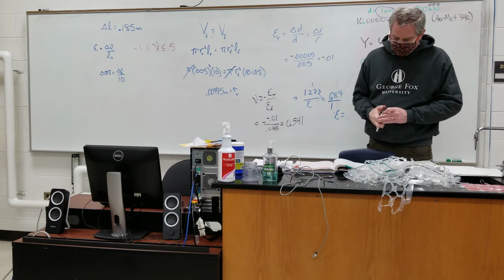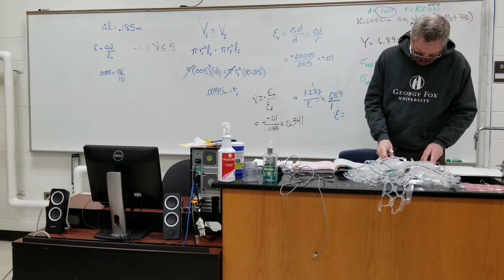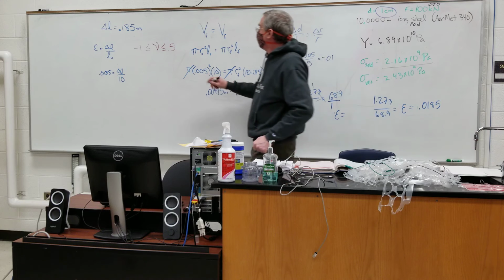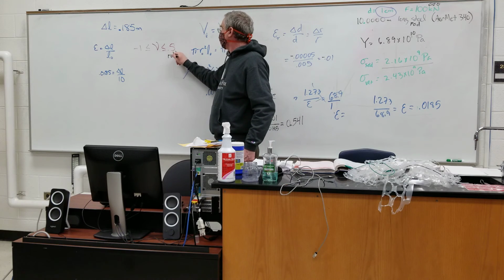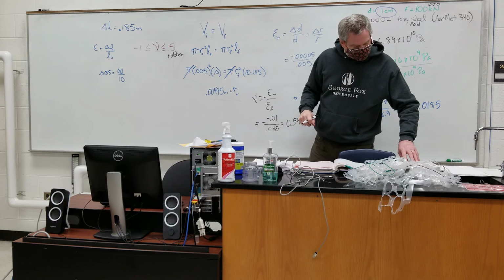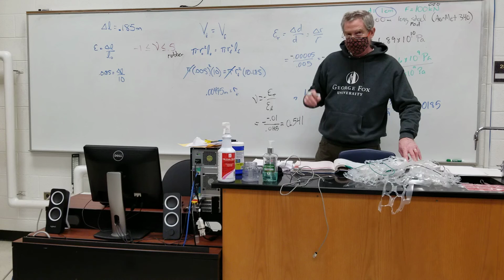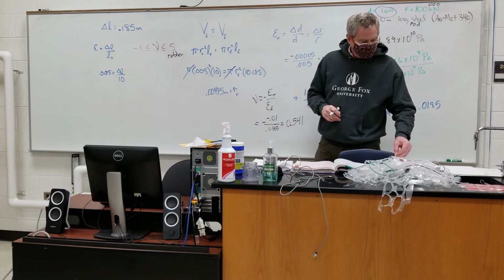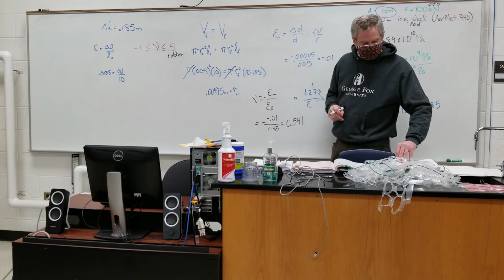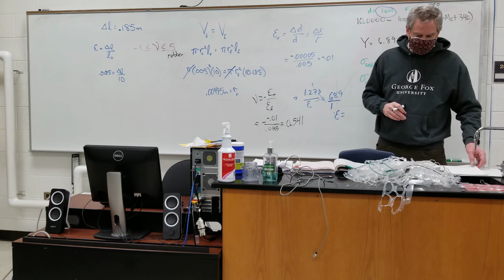Now, in terms of realism, I do have numbers here. Rubber is 0.5. That's at the maximum. Cheese is 0.45. Copper and steel typically 0.3, aluminum 0.35, concrete 0.2, cork 0. Most steels are in that mid-range, somewhere around 0.2 to 0.3.